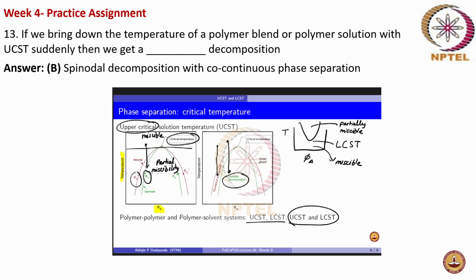Will it crystallize? No, it's not about crystallization. It's about the phase separation. Nucleation here means that the separation starts, because above the upper critical solution temperature, the blend is completely miscible. It forms a single system. Whereas here it starts phase separating. So A starts separating from B, so small patches of A start forming if it is a binodal decomposition, and then these start increasing in size. It doesn't mean that there is crystallization and all. It is more about phase separation. Okay, got it.